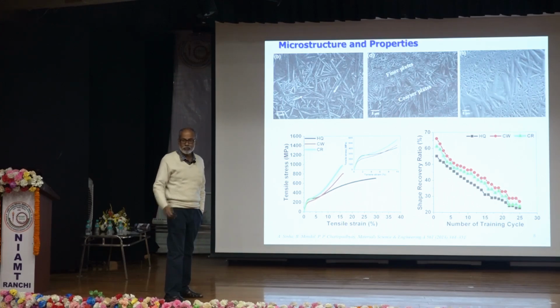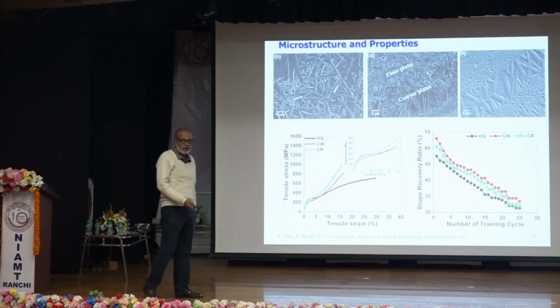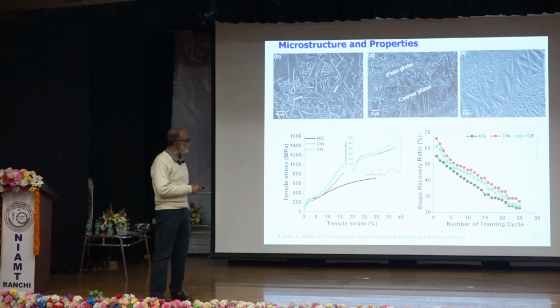When we were deforming, although we were deforming in cryogenic temperature, by virtue of limitation in conductivity, some region of material in a very localized manner gets heated adiabatically, and it has been reported in literature also. In case of copper, it can go as high as 500 degrees centigrade. So this localized heating transforms the martensite to austenite. And during this heating, the strain is relieved, and when this austenite attains room temperature, there is cooling, and this austenite or B2 phase transforms into martensite, which is having coarser size because it is unconstrained. There is no strain now. So we have this kind of microstructure.